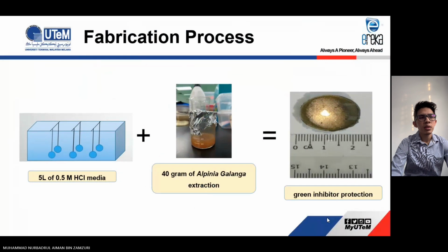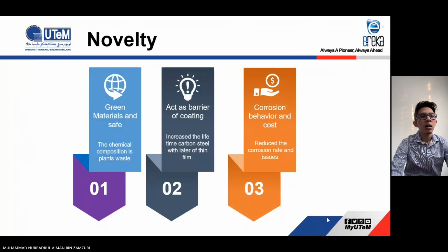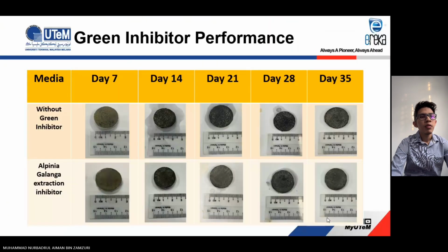For the fabrication process, in order to produce a layer of green inhibitor protection, 5 liters of 0.5 molar hydrochloric acid media is mixed with 40 grams of Alpinia galanga extraction. Then we will have a green inhibitor protection on the low carbon steel. Our product came out with 3 novelties that cover green materials and safe, act as a barrier of coating, and corrosion behavior and cost.